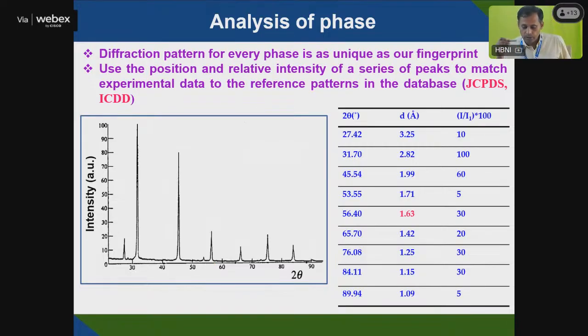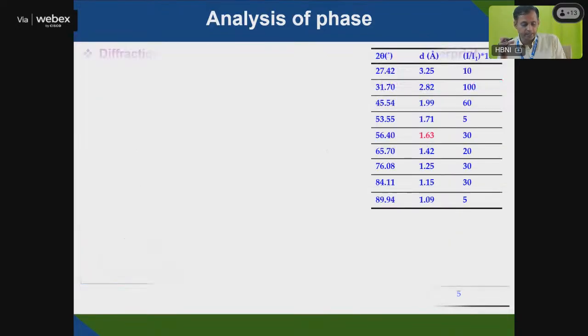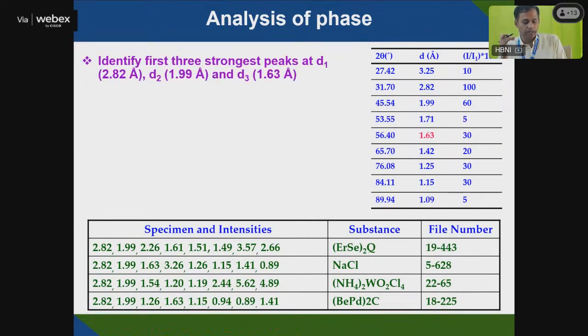In these peaks, what I identified, I have shown the different d-spacing and intensity. My maximum intensity peak is at 31.7 and the other peaks are there. After getting this, first I have to see the database available, either called JCPDS, Joint Committee for Powder Diffraction Standards, or ICDD, International Centre for Diffraction Data. You can take either of the two, and then you can see how to analyze.